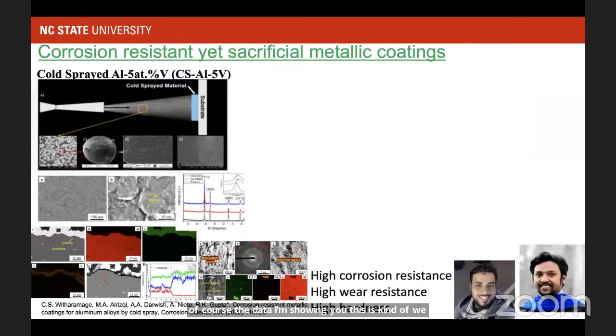But when it comes to making real parts, one aspect would be making some structural components. Another would be using them as a coating. So this particular example shows some of those metallic coatings by cold spray, where we can use our material, aluminum vanadium in this case, as a feedstock. So we know that in cold spray we have a substrate and we deposit our metal powder on the substrate. We send the powder particles with very high velocity, and the particles hit the substrate and get cold welded on it. In that way, we develop a coating on the substrate.